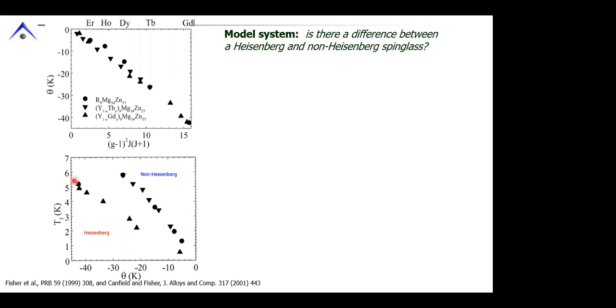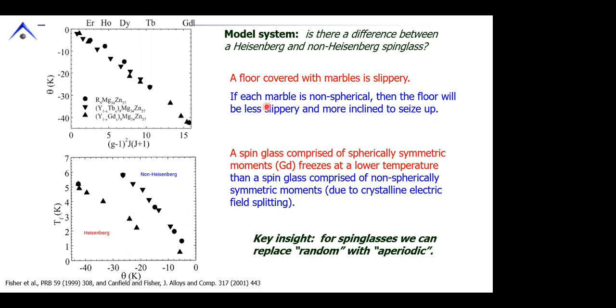We can also measure the freezing temperature and plot the freezing temperature versus the theta, two experimentally measured quantities. And we can see this break up into two very clean manifolds, a Heisenberg manifold for the gadolinium and the gadolinium dilution with yttrium, and a non-Heisenberg manifold. Okay? Now we can understand this if we have a simple analogy.